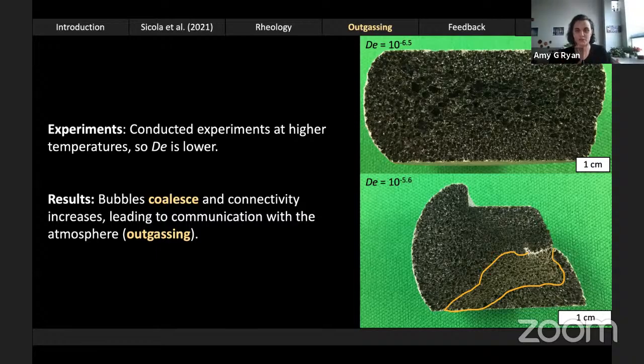But it's at these Deborah number conditions that I observe, for the first and only time, bubbles coalescing. It's a little bit hard to see, but there are a lot of outsized bubbles in the center of this core here. Normally bubbles are about that shape or size. I also observed large regions of oxidation, despite there being no fracturing, perhaps again indicating that connectivity was formed at these low Deborah number conditions, leading to whole-scale outgassing of the foamed core.